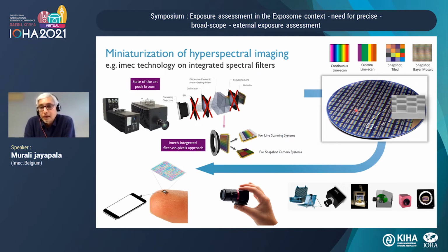Just to illustrate a little bit, the filters that I talked about, we can deposit them directly on what we call image sensor wafer devices. This is a 200 millimeter image sensor wafer, which typically houses hundreds to thousands of sensors, and we can deposit and pattern these filters at pixel level, with very high accuracy at micron or even submicron level, and we can pattern them in different ways: line scan, snapshot, or even per pixel level. Once you do this kind of deposition, the advantage is that your whole spectral sensing device becomes this small chip, and then the electronics around that can be miniaturized.